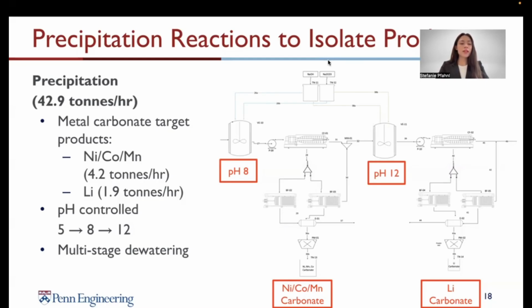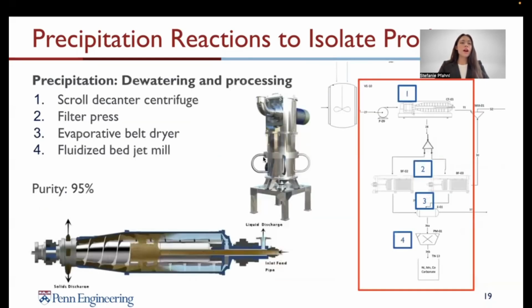The filtration process is done through a multi-stage dewatering process, which includes a centrifuge, a couple of filter presses, a belt dryer, and a fluidized bed jet mill that gets us to a dry solid powder that is very fine and has a purity of about 95%, which is below battery standard, but above industrial standard to the point that we're able to sell it to battery manufacturers or other industrial users of lithium, nickel, manganese, or cobalt.